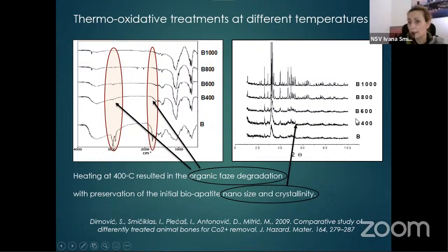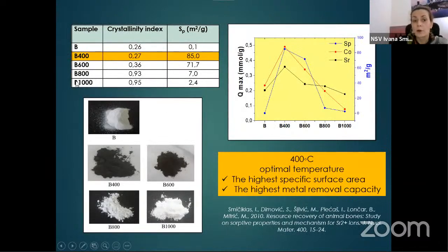But the product that was obtained at 400 degrees Celsius has low crystallinity, similar to the original bone, while with the increase of the temperature, the agglomeration and sintering of bioapatite nanocrystals takes place, and the obtained product has much higher crystallinity. As a consequence of higher crystallinity, the products obtained at elevated temperatures have much lower specific surface area than the product that was obtained at 400 degrees. This is the physical appearance of these products, and it can be seen that the product at 400 degrees is gray due to the carbonization of the organic phase.